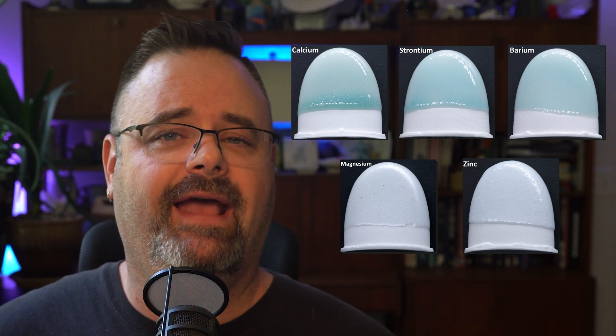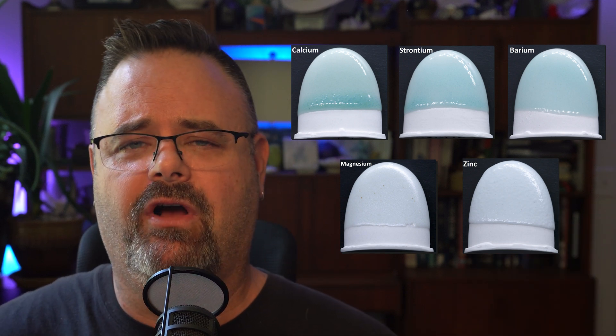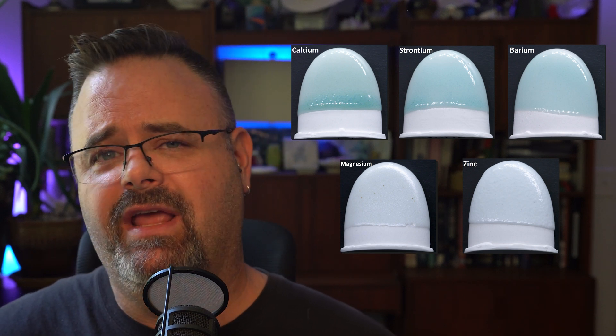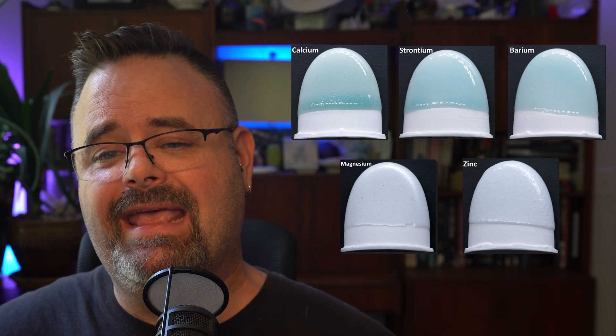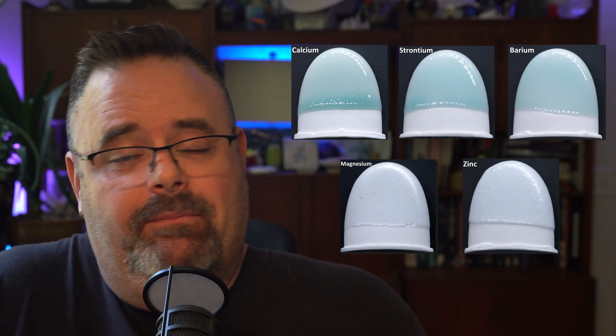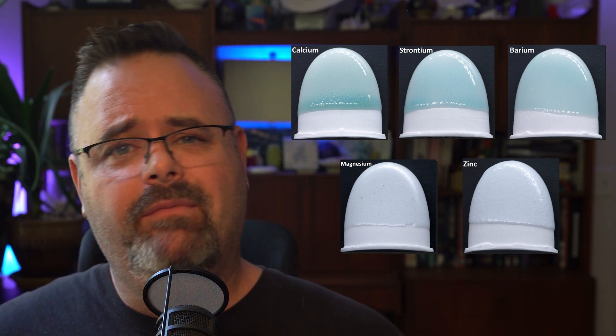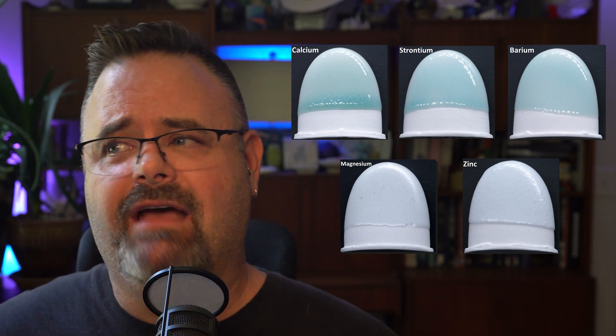Bristol reactions are not just limited to whiting and zinc. We have five different alkaline earth fluxes: magnesium, calcium, strontium, barium, and zinc. We need zinc for the Bristol reaction, but calcium can be switched out. Calcium, strontium, and barium will all create a Bristol reaction with zinc. What doesn't work is magnesium and zinc — the chemistry of magnesium and zinc are just not compatible. Pure zinc also won't work on its own. But strontium-zinc, calcium-zinc, and barium-zinc will all create a Bristol reaction.